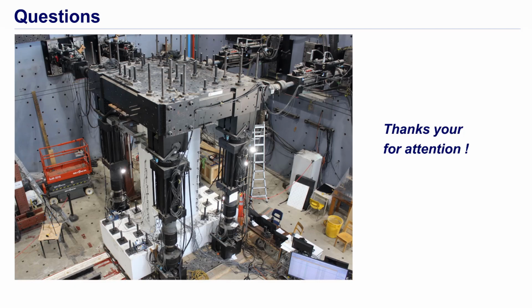I mean, there will be some residual deformation, but beyond that, I would say the beauty of it is the amount of damage will be no more than what you would see in conventional design using cast in place. The beauty is also you can select where it's going to happen and which part is going to yield. So you get a much better control on your design using a combination of UHPC and sleeves. What I propose here is just model number one. That can be improved in different ways depending on which design, target, displacement, and behavior you want to have.